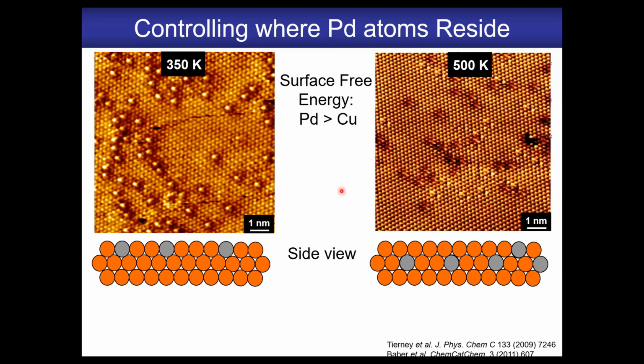And then if we go to a higher alloying temperature at 500 Kelvin, you see mostly dark spots there. And that's because palladium has a higher surface free energy than copper. It has more of a tendency to be surrounded 12 coordinate by its host. So thermodynamically in a vacuum, palladium would rather be underneath the surface or in the bulk, as apparent here.